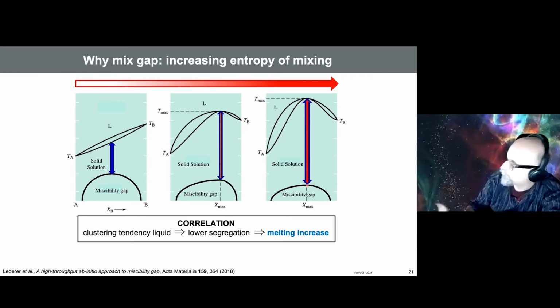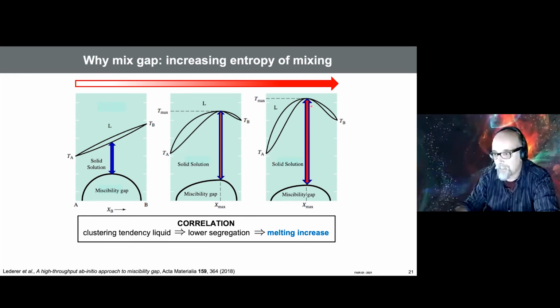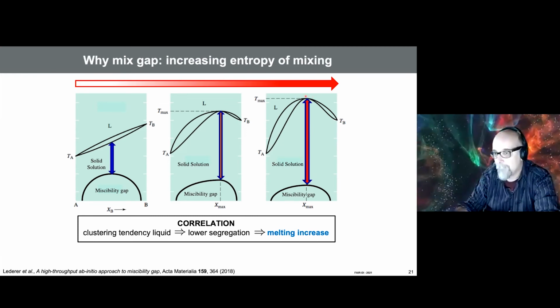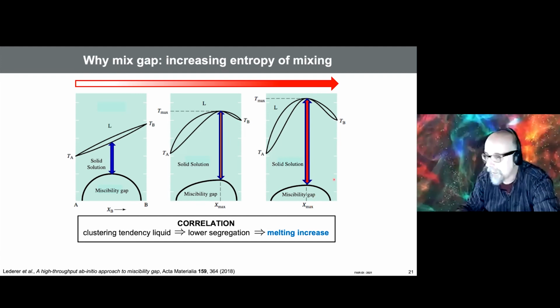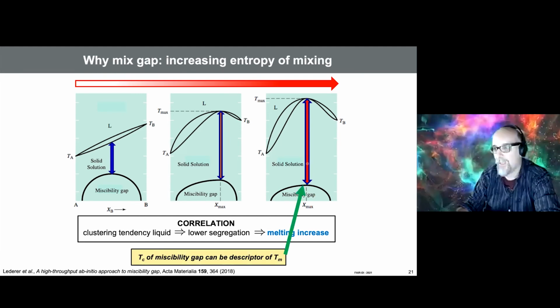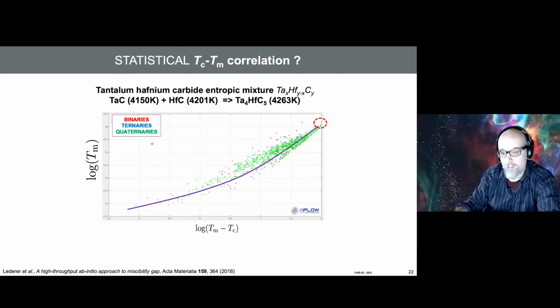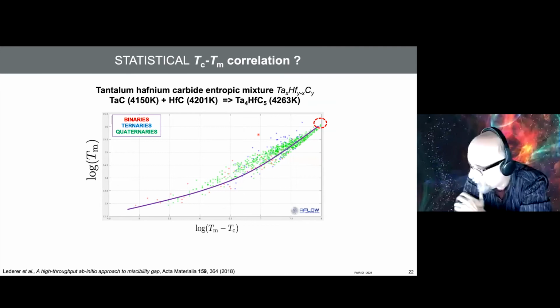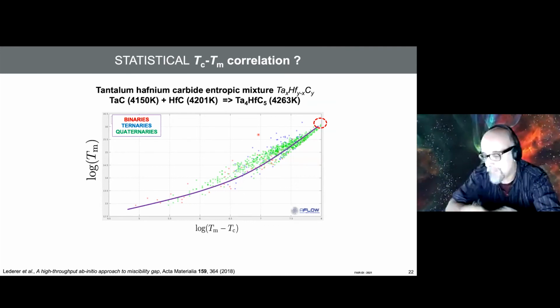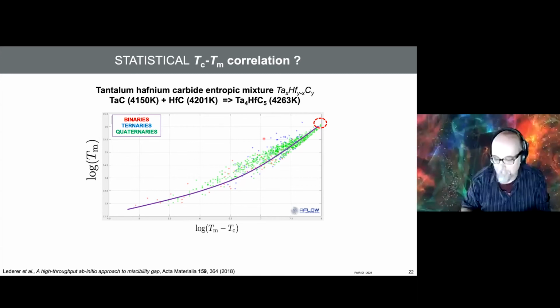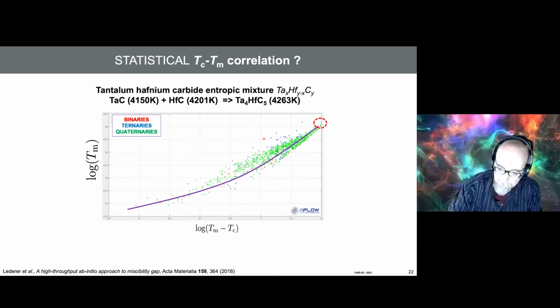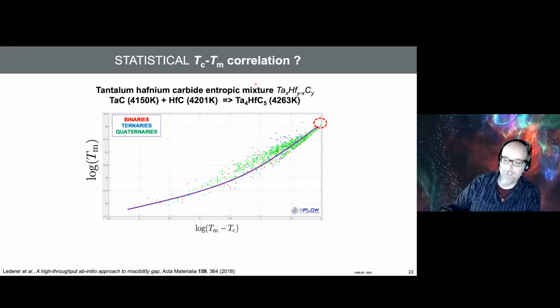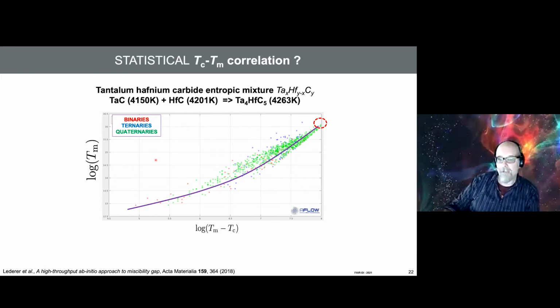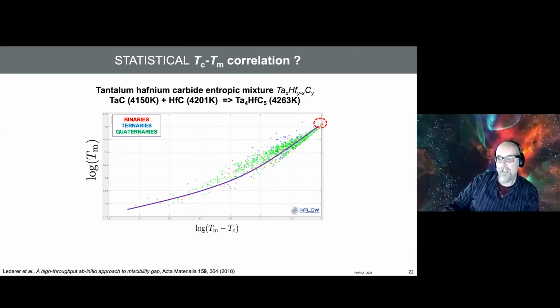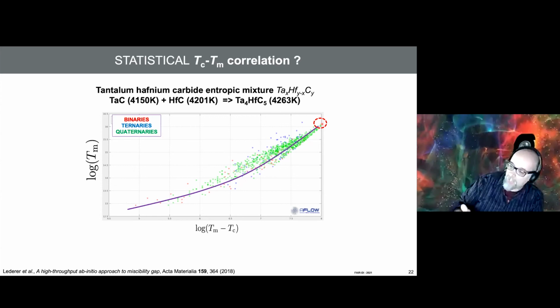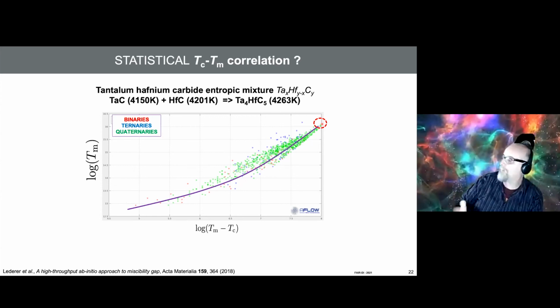Okay, that's what we were doing a couple of years ago, right? So instead of getting a very high melting point, you get a very low miscibility gap in systems forming solid solutions. Okay, that was the trick. This came from analysis of literature, the books that Matthias mentioned before, where they were all already digested in CALPHAD and in the ASM phase diagram books. Okay, so then we did some extra CALPHAD, and you see that if you increase the number of species, you actually increase the melting point. So you want to increase entropy and make the materials more refractory, right?